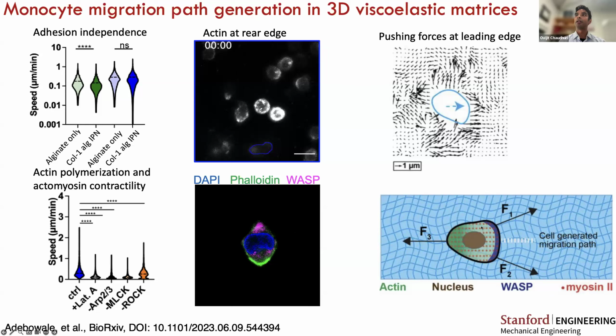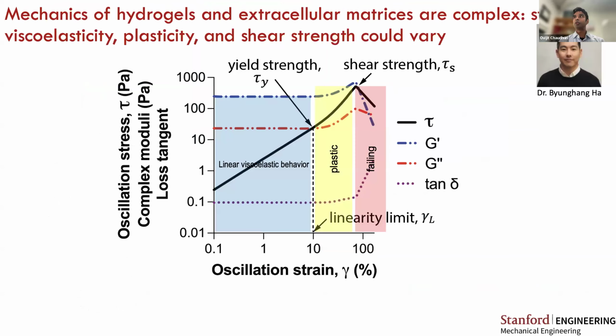And so overall, what these studies suggest is that as these monocytes are migrating, we have WASP at the leading edge that's initiating formation of this growing dendritic actin network. And this generates protrusive forces that are pushing on the hydrogel. And then the myosin activity is acting to induce retrograde flow of this actin so that it accumulates as this dense puncta at the rear. And then in terms of the force balance, we see that cells are pushing off their rear in many cases, but sometimes off of their sides. Okay, so I'll end this.